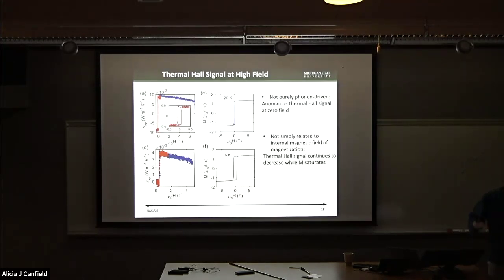Okay, so what's the mechanism of the very nice thermal signal that we observe? Is it purely driven by phonons? The answer is no. The reason is that if the thermal signal were purely driven by phonons, we would expect it to increase with the magnetic field, and at zero magnetic field the thermal signal should be zero. But in reality, we observe a thermal signal even at zero field. So this tells us it's not purely driven by phonons, and we can exclude such a possibility.